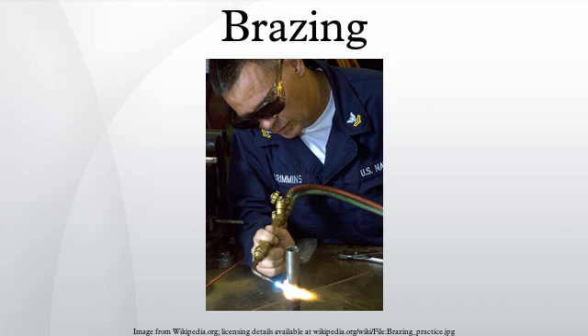The use of flux or self-fluxing material is required to prevent oxidation. Torch brazing of copper can be done without the use of flux if it is brazed with a torch using oxygen and hydrogen gas, rather than oxygen and other flammable gases.